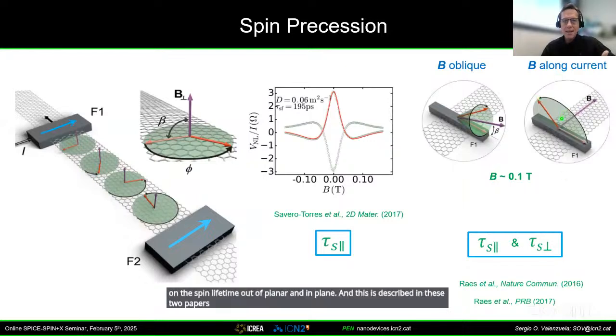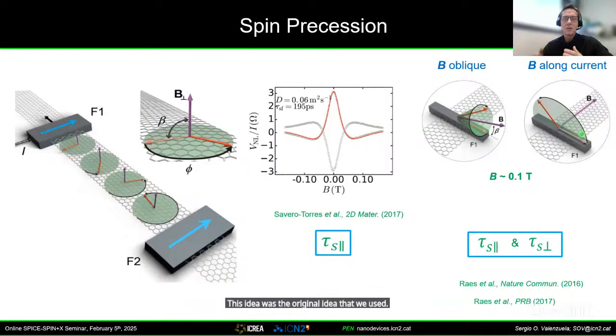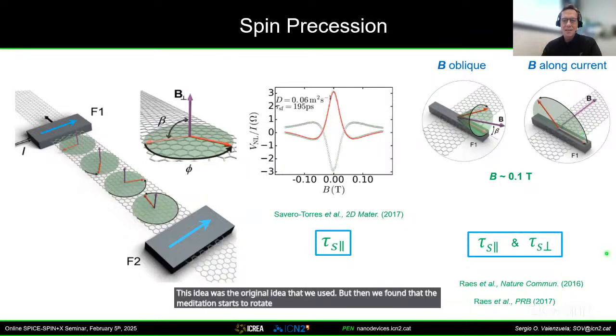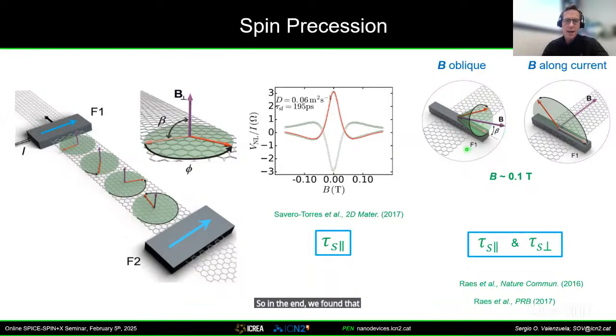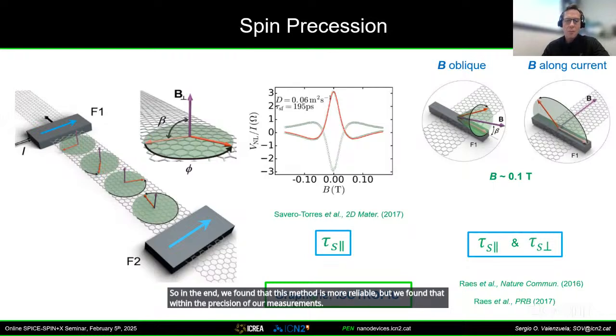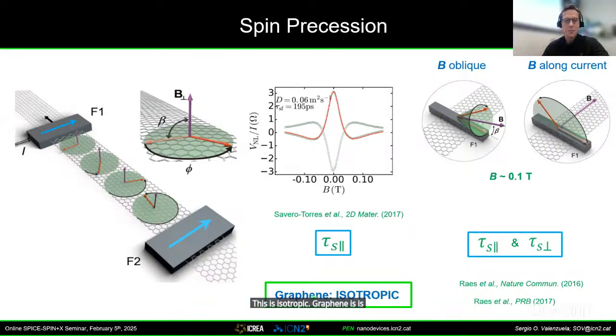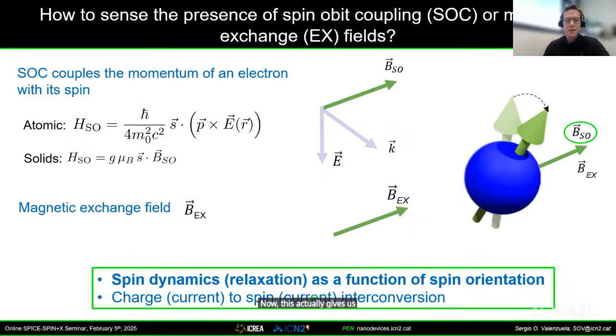This was the original idea that we used, but then we found that the magnetization starts to rotate, and getting this spin lifetime is not very accurate, especially when the anisotropy can be small. So in the end, we found that this method is more reliable, and we found that within the precision of our measurements, graphene is isotropic, independent of the spin orientation. Now, this actually gives us a nice opportunity. We now have a spin channel, graphene, which is not anisotropic. And then we can look at a region in which we have these spin orbit fields that can induce the anisotropy.